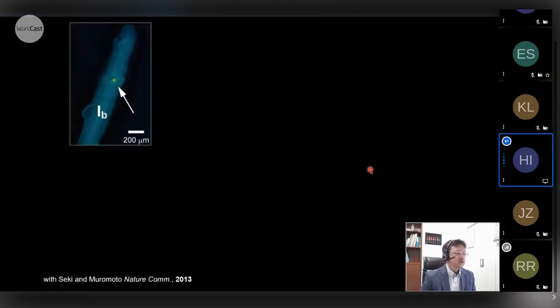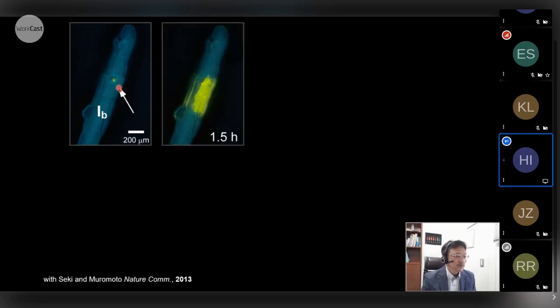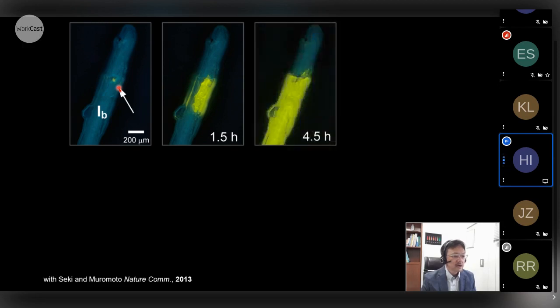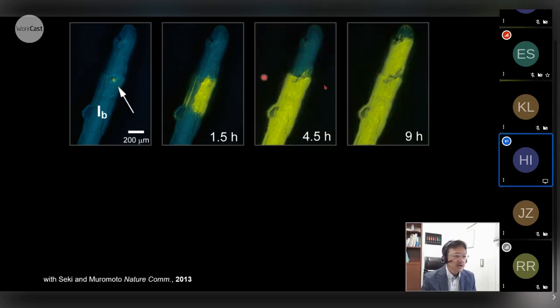Okay, these results give us some very interesting ideas. So maybe there is some kind of amplification effect of mechanical stress for a crystal phase change. One of my students tried to put some very small mechanical stress on the surface of the crystals to make a yellow spot. Surprisingly, this spot spontaneously developed across the crystal just after 9 hours. This color change was induced by very small mechanical stress on the surface.